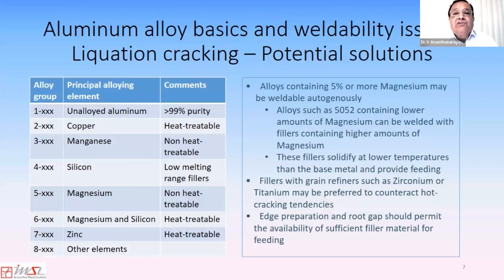And some of the potential solutions for this liquation cracking is to, if you are doing arc welding, use filler metal containing 5% or more magnesium that lowers the melting temperature of the filler metal and allows it to provide a feeder for already solidified regions, so they solidify without cracking. And also fillers with grain refiners such as zirconium can help as well. And edge preparation and root gap can also be done in such a way that sufficient filler metal feeding is enabled during the cooling of the weld post-welding.